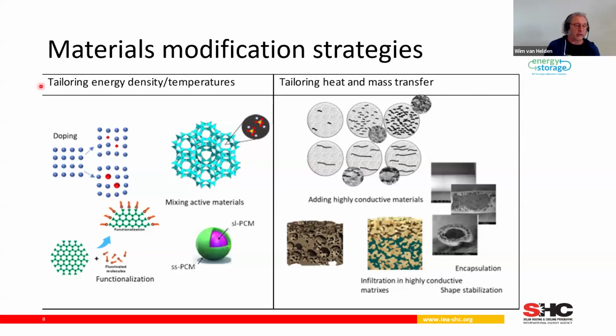First, for tailoring the energy density or for tailoring temperatures. One method is, especially with salt hydrates, to work with doping, so that materials are doped and therefore the crystal lattice is changed and therefore the uptake of, say, water vapor or other vapors is increased or decreased. So modifying then the enthalpy of the material. Another way is functionalization. Here, a PCM material is added with a surface active agent in order to increase or, in this way, to decrease the hydrophilicity of the material.